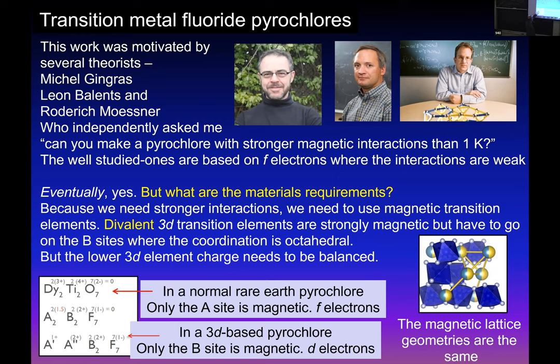This is the big atom site. This is the octahedron site, which has to have no spin. And then there have to be 7 oxygens. But the problem is, if you want to make that with something that has a bigger spin, I have to go from f electrons, which are near the nucleus, to d electrons, which are further out. If the d electrons are further from the nucleus, they're going to interact with each other more strongly. The pyrochlore lattice is a particularly good lattice for frustration because it's made of interpenetrating tetrahedra, so I can put something with d electrons in the lattice and get it to work.